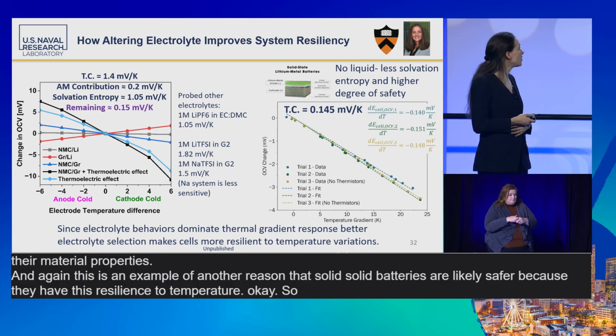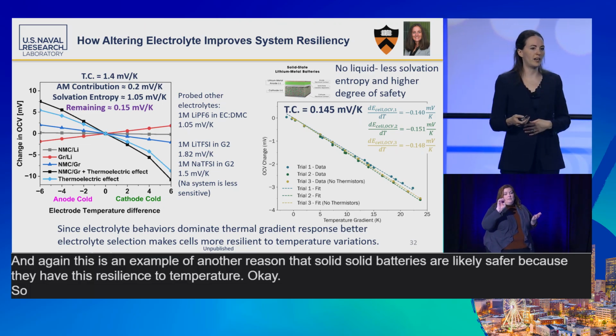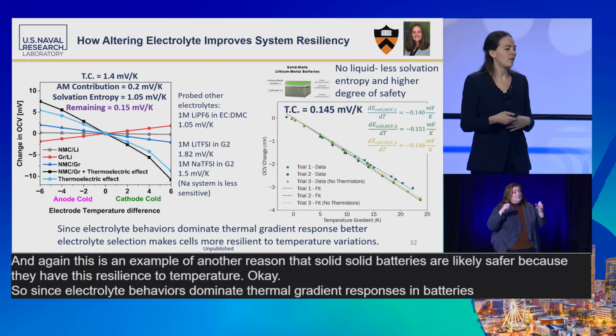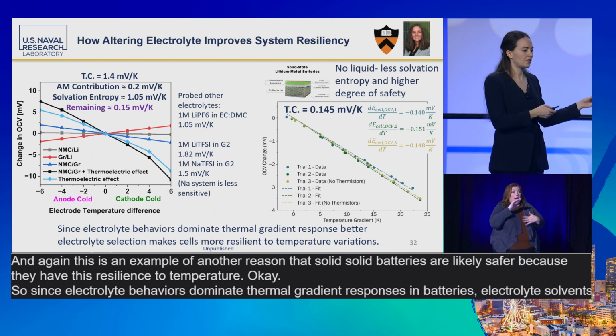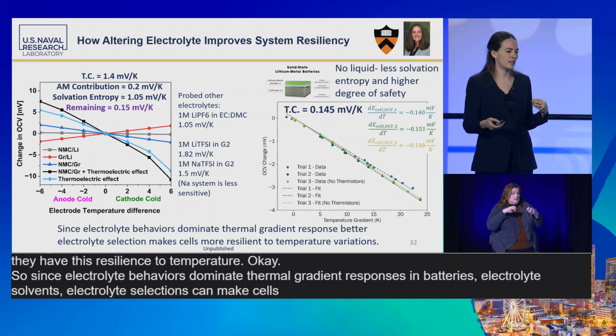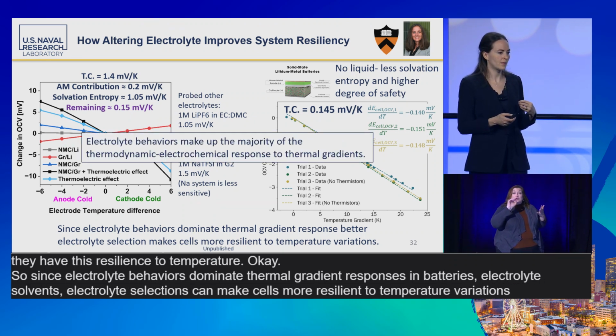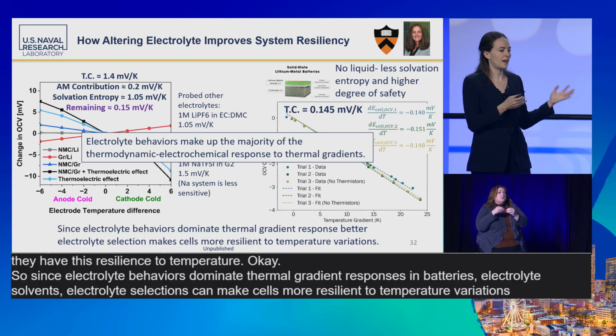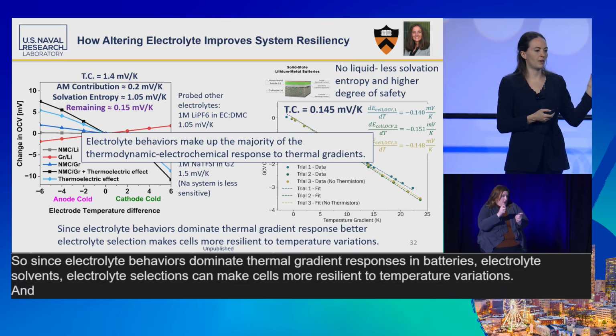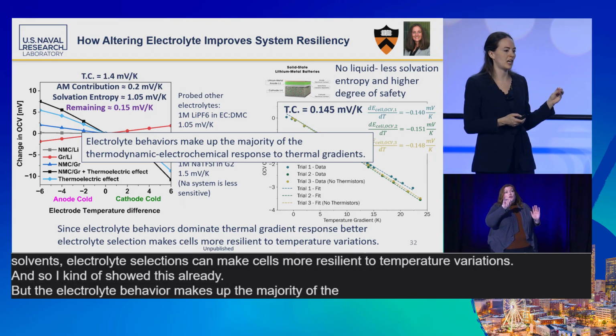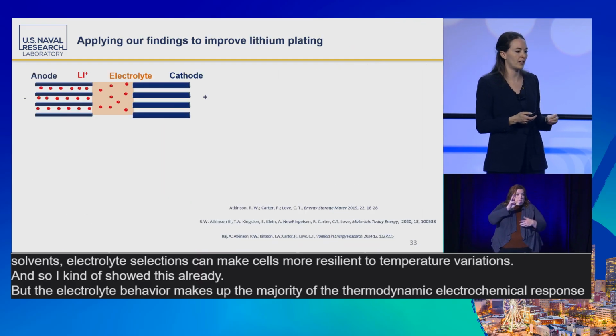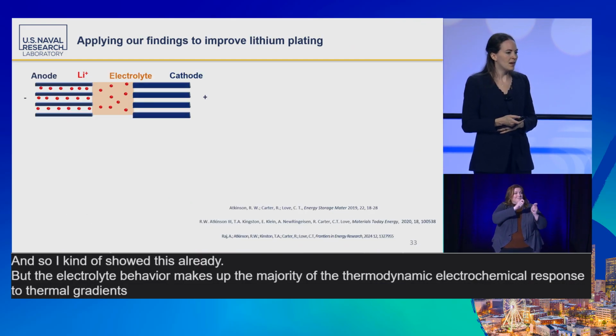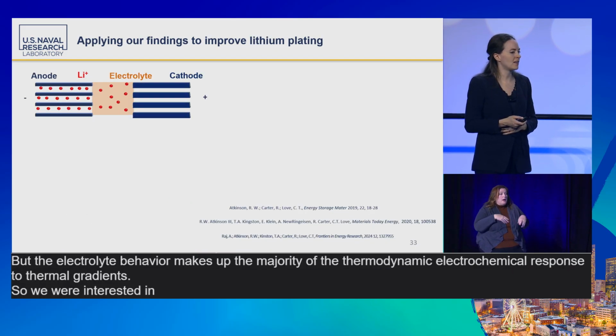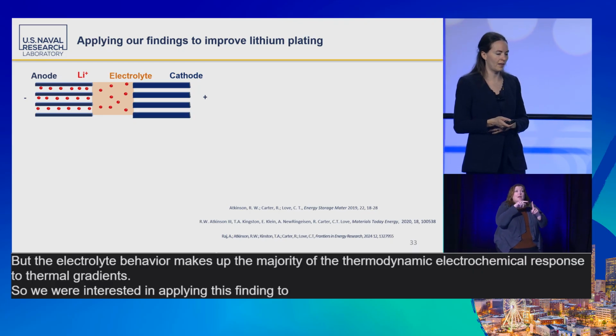Okay, so since electrolyte behaviors dominate thermal gradient responses in batteries, electrolyte selections can make cells more resilient to temperature variations. And so I kind of showed this already, but the electrolyte behavior makes up the majority of the thermodynamic electrochemical response to thermal gradients. So we were interested in applying this finding to intentionally plate lithium metal.